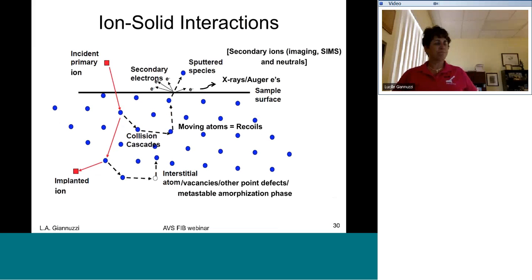So you have an incoming incident primary ion. And again, this can be gallium, neon, helium, whatever it is. This is going to come in and get bounced around, similar to a cue ball hitting a bunch of billiard balls. So this is going to generate, particularly for heavy ions, what's called the collision cascade or the recoils. So these moving atoms inside of the solid are the recoil atoms. This generally results in an implanted ion. This can also result in internal defects in the material.